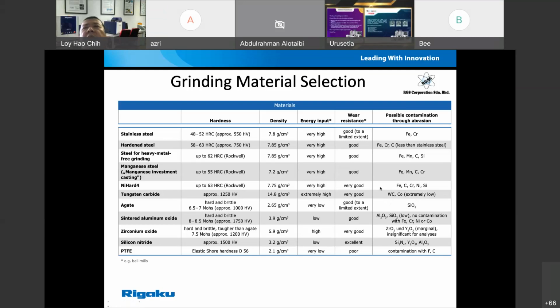But let's say your element of interest is tungsten, carbon, or even cobalt inside your samples. Then you should avoid using a tungsten carbide vessel. In that case, which vessel are you going to use? A lot of times people will go for zirconium oxide. The hardness is also very high, about 1350 HV. It will contaminate your samples with either zirconium oxide or yttrium oxide. So if these are not the elements of interest in your analysis, then you can select these two. But even then, the contamination levels of these two are actually quite small.